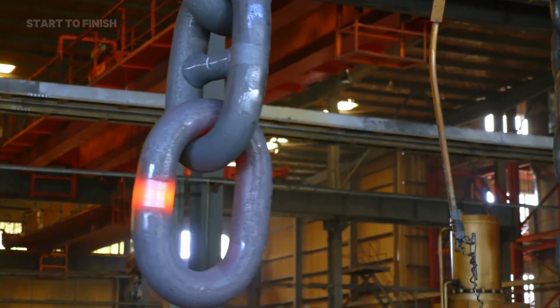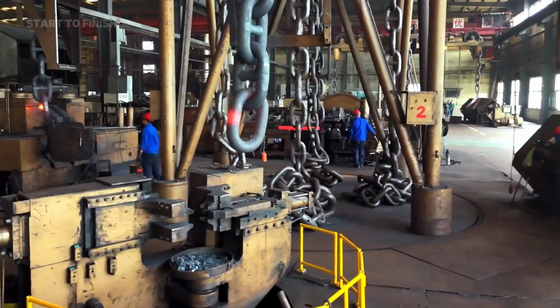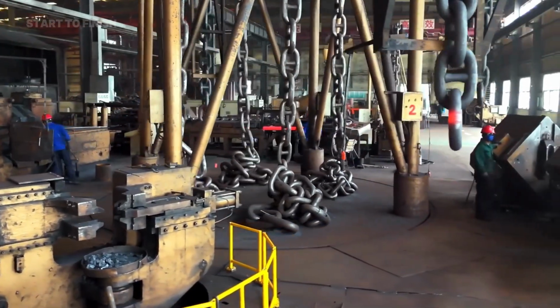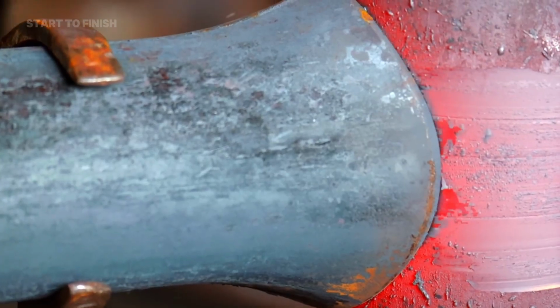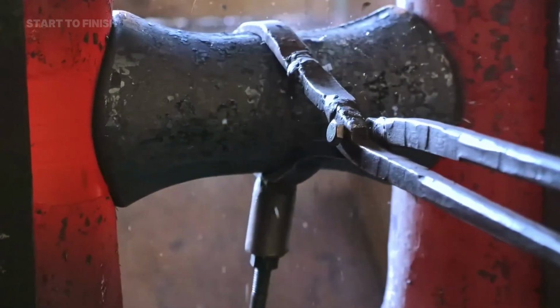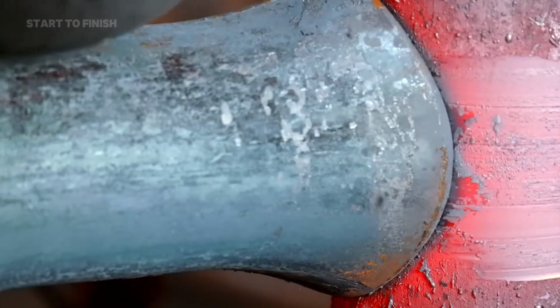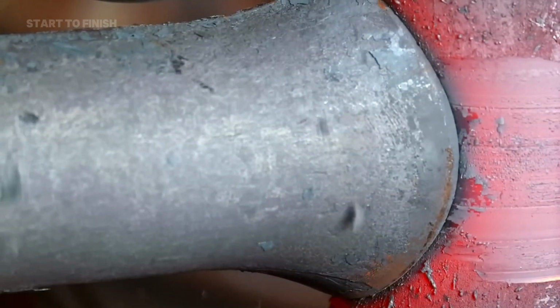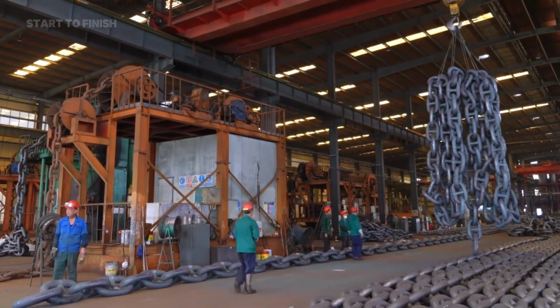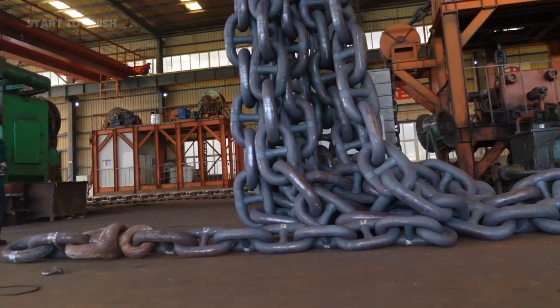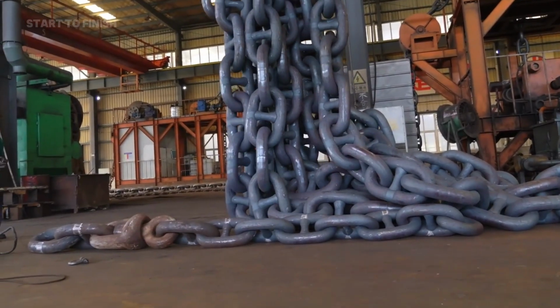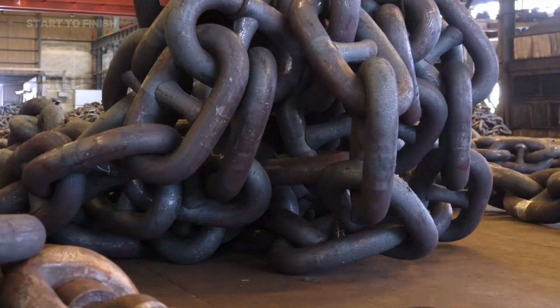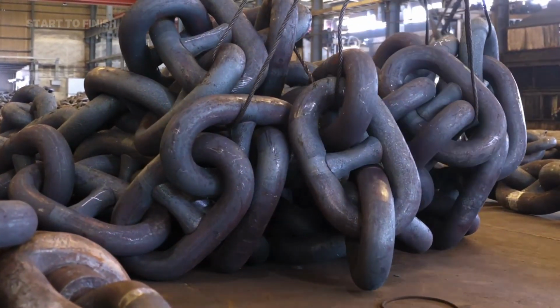They move through a rotating heat treatment drum, which gradually lowers the temperature under controlled conditions. This annealing process relieves internal stress caused by forging, preventing cracks when exposed to the extreme forces of the open sea. Once cooled, robotic handlers transfer the chain to an automated trimming station, removing any surface excess and sharp burrs that could compromise coating or strength.